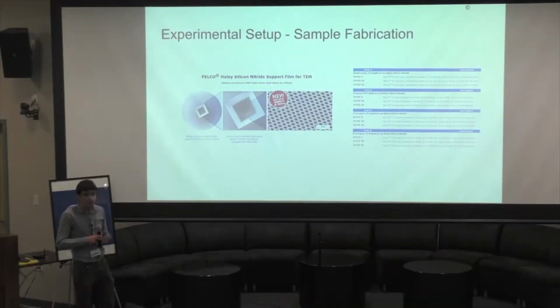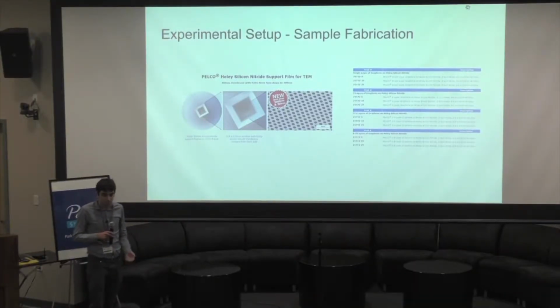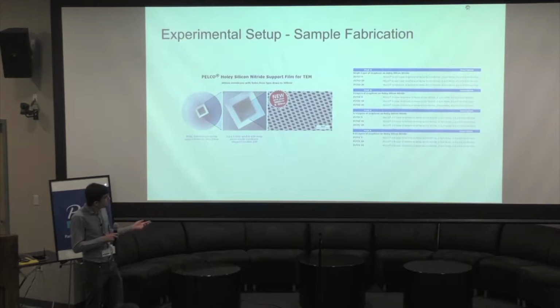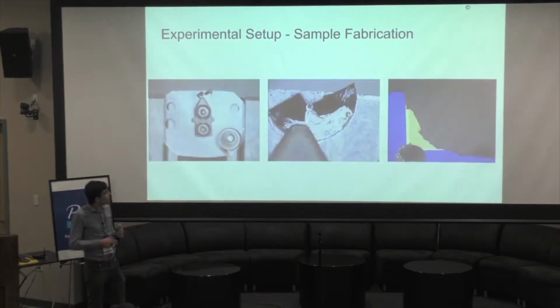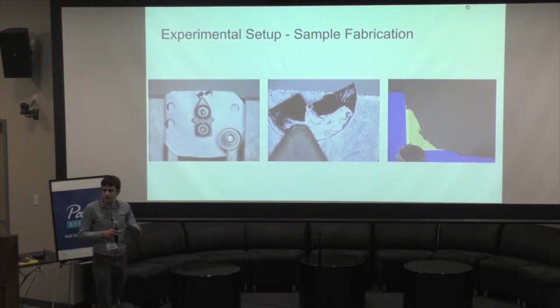So the sample preparation for this project was particularly involved. We went on the internet and we found these graphene over holey silicon nitride grids designed for transmission electron microscopy. They have 2.5 micron holes on a 4.5 micron pitch covered with monolayer graphene. So we bought some of them. We broke them in half so that we had a clear surface to access with our microscope, and we stuck them to the sample stage.